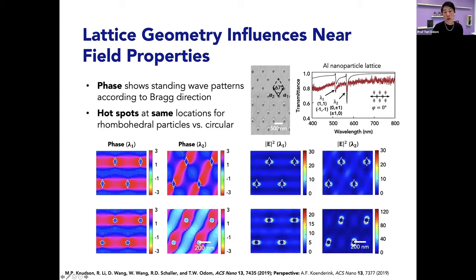But what's interesting is that if we look at the hotspots at these same locations, at these different wavelengths, λ1, the shorter wavelength, and λ2, the longer wavelength, they are in the same positions for the rhombohedral particles, these diamond-shaped particles. So they have overlapped hotspots. The hotspots are in the same positions along the short axis, but at different wavelengths. This is quite interesting. And I'll show you the outcomes of that in just a minute. But you'll notice that if we keep the lattice the same, but have the unit cell be symmetrical, the fields will go along with the polarization. So here we've forced the hotspots to remain where we want them.